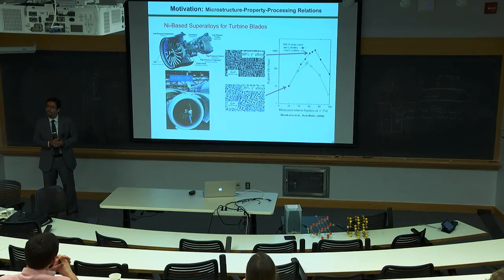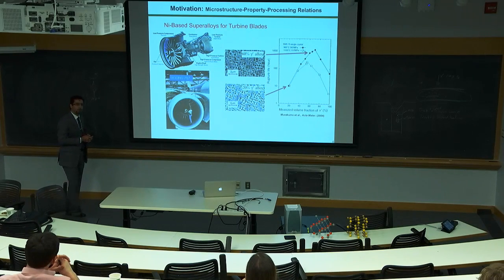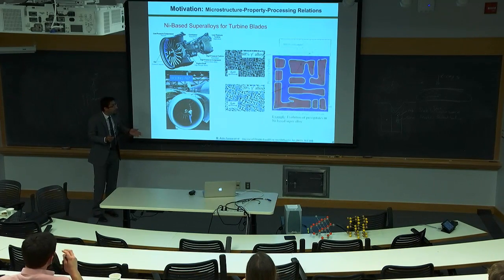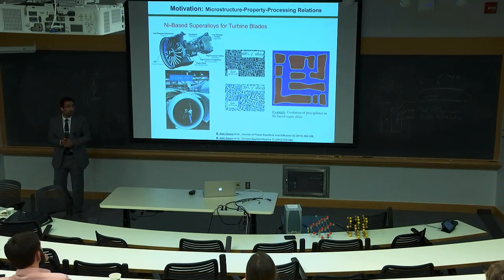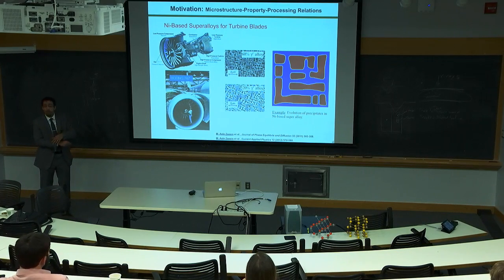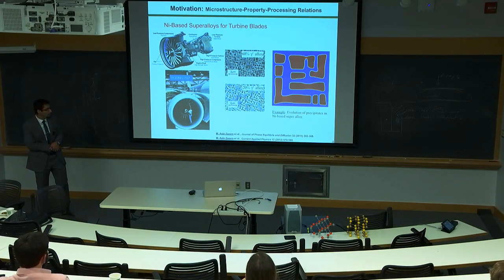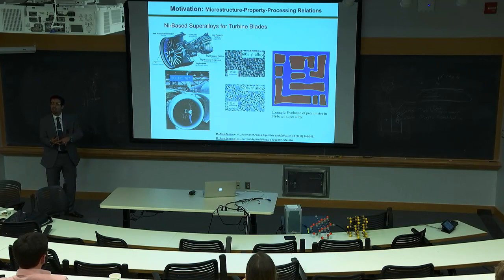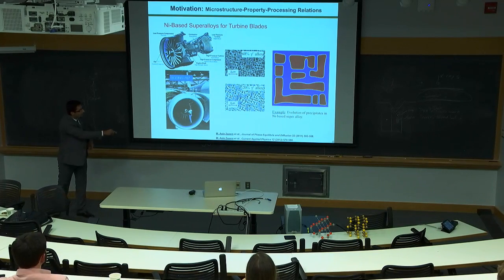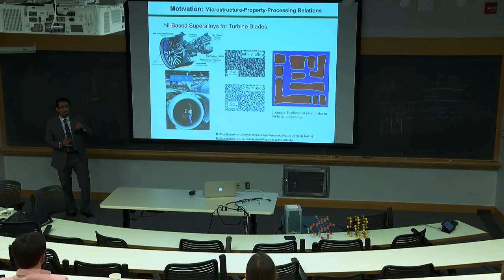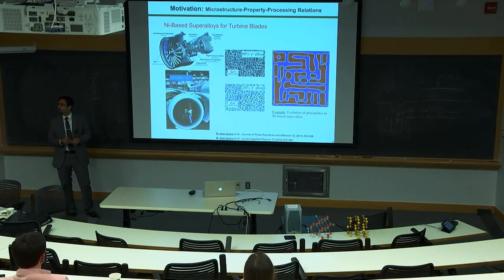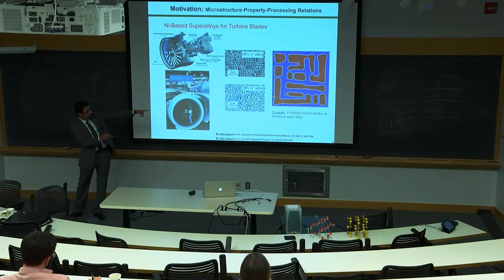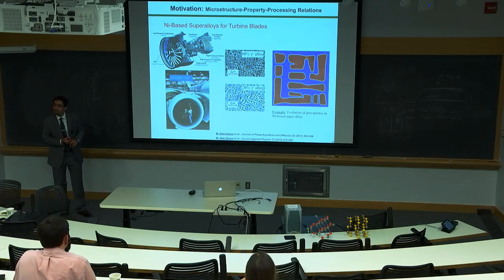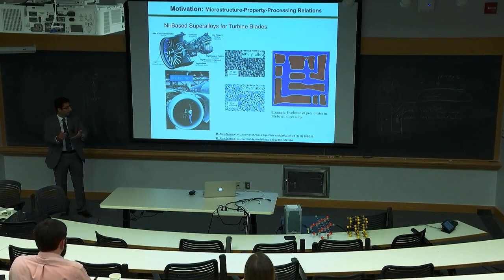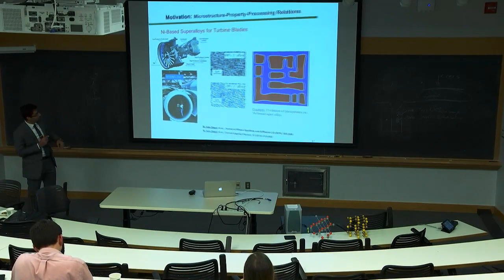We need to understand the mechanisms controlling nano and microstructures. And for this example, we developed a model. It's a phase field model. What it gives us is the size, shape, and volume fraction of these particles based on the composition and heat treatment condition. So basically we can predict what is happening, and we can guide experimentalists and industry. So this was for that example.